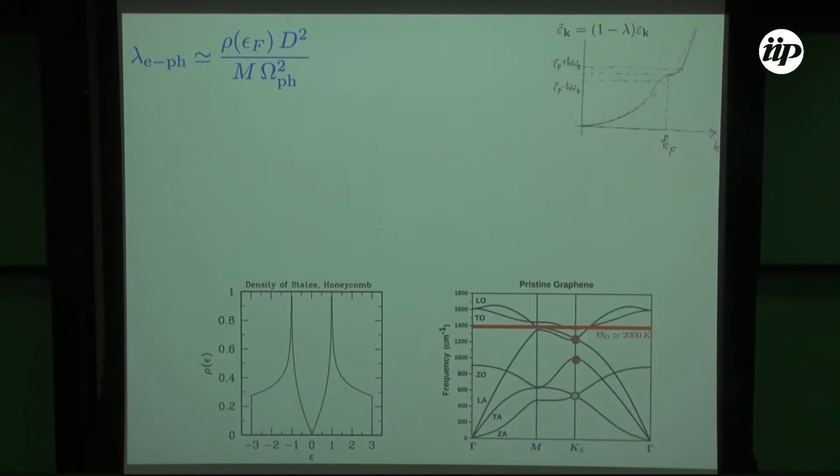But on the other side, we are needing a coupling to the phonons. And if you are looking for the pristine graphene phonon dispersion relation, you need a coupling to the phonons which are having a proper quasi-momentum. And there are 3 acoustic branches, but unfortunately that one, which has the lowest omega, is not coupling, for symmetry reasons, to the p electron. Only those phonons which are higher energy are coupling to that.